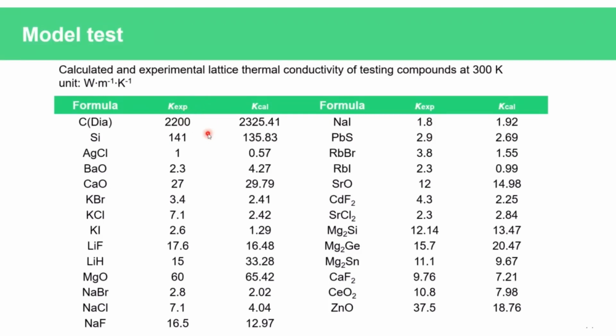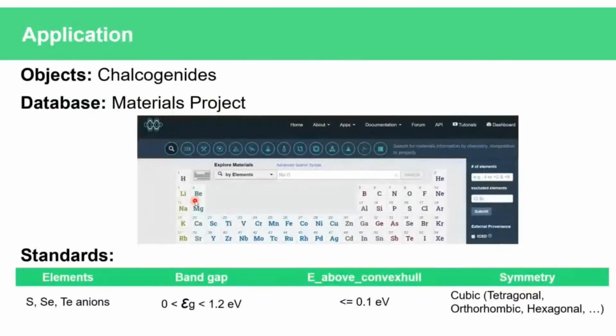Another index I use is the root mean square relative deviation, which is a measure of the quantitative difference between two variables. The root mean square relative deviation here is around 30%, meaning on average the calculated kappa value is 30% different from the experimental value. I think this accuracy is relatively high.